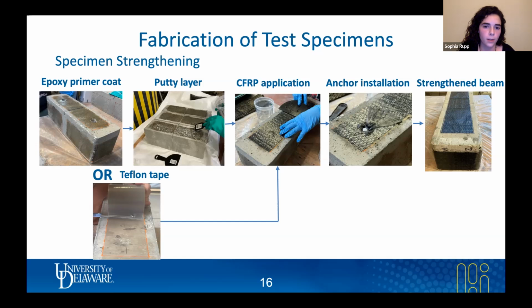and then go ahead onto the third step, which is saturating your CFRP or saturating your carbon fiber, applying it to the concrete surface, and then going ahead and embedding your anchor into the anchor hole, splaying it out over the CFRP that was applied. And then finally, you add those shear wraps around the sides, and additionally a square patch over the anchor and the anchor hole to give it more of a finished look.